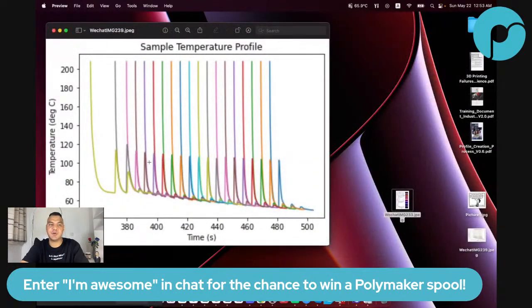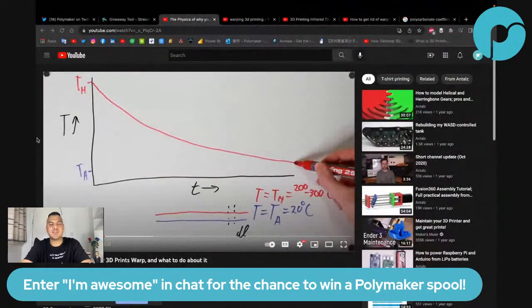From our experiments, this is the model we have developed, and the simulation is very, very close to the experimental results. So it's way different than exponential. I mean, it goes almost directly to ambient temperature. Maybe not ambient temperature, but definitely not exponential. So that's another hypothesis that may need to be proven. I have data. Maybe he has data. We can just compare.